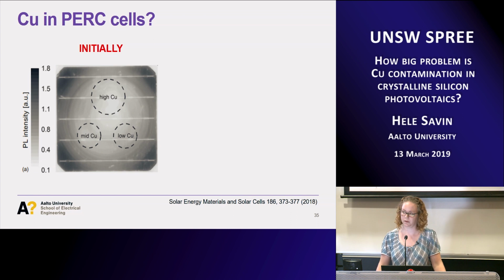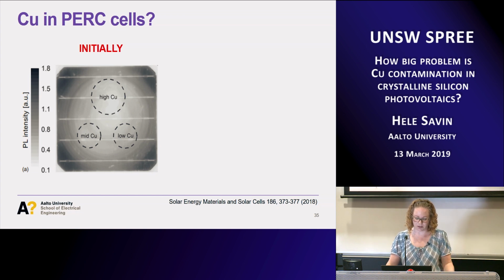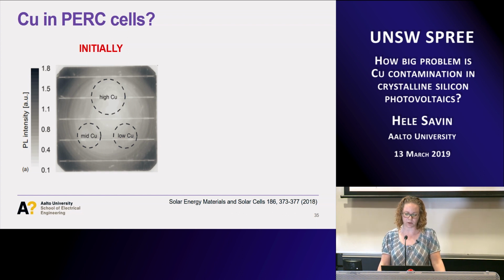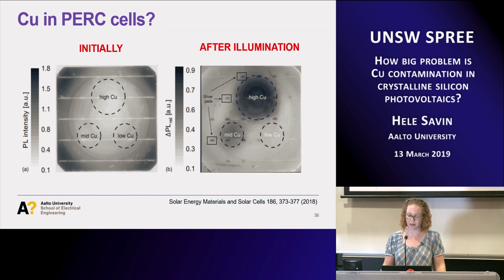Okay, then we were quite convinced that this is a problem in PERC cells as well. So we also repeated the experiments by making, in collaboration with an industrial company, PERC cells in their process. And we again used the same droplets that we have used in the past. They processed PERC cells as they usually do, and then they measured PL after the cells were finished. And again, initially you don't see anything, but after you do the light soaking, you actually see the copper spots appear again. So there you are, you have the copper LID clearly taking place in PERC cells.